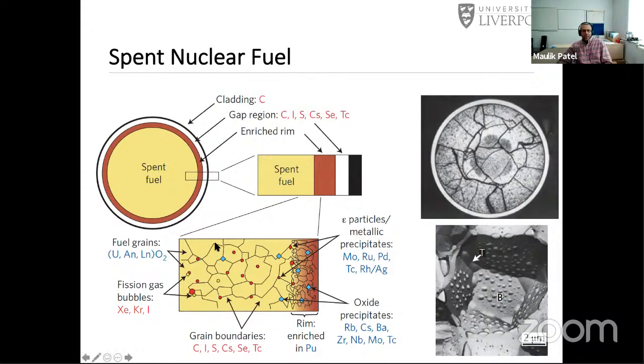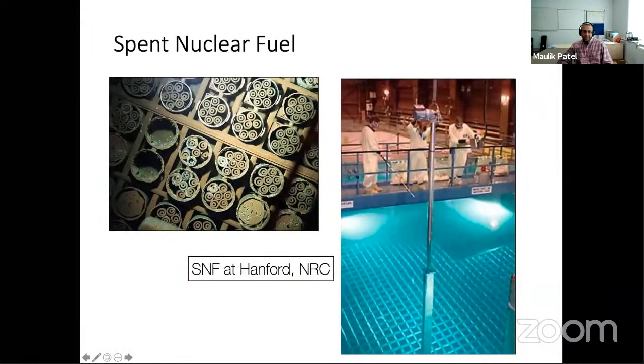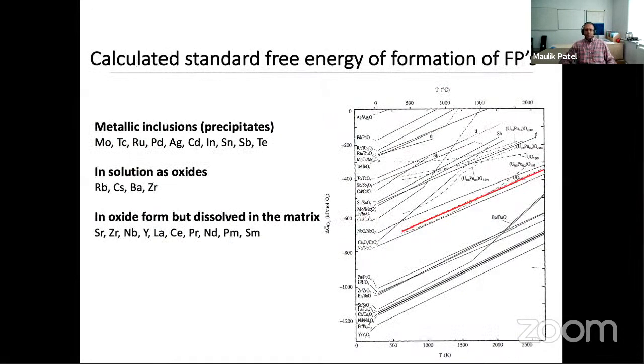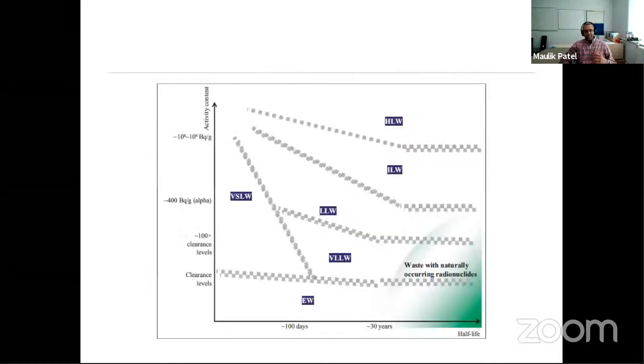The spent nuclear fuel is either stored in a cooling pond or in dry casks, because you have species like cesium and strontium, which have half-lives of about 30 years or so, and we'll see what happens because of those. The fission products can also form new compounds in the fuel, so your fuel properties are changing as a function of time. Now, what you're left with is lots of waste. Well, it's deemed as waste in lots of countries, and if you reprocess it, your level of waste goes down.